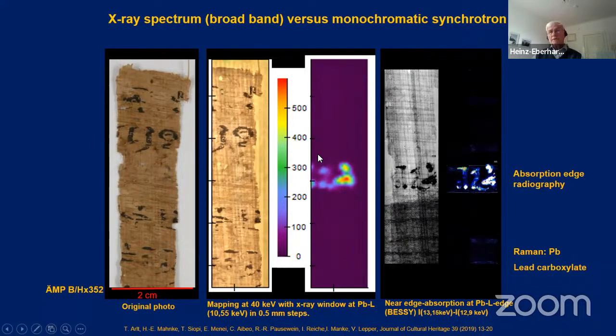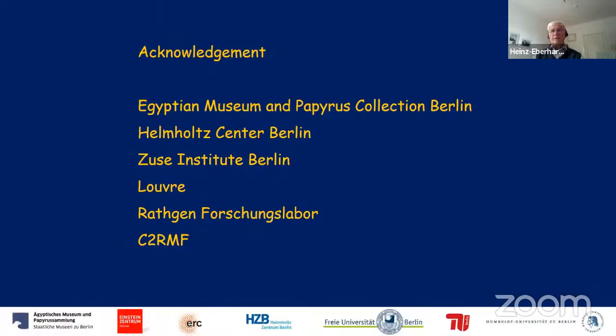One can see it much better, of course, much clearer, with better equipment on a synchrotron beamline, where you have the sharp focus and where, in fact, we did the L-edge sensitivity, going above the edge and going below the edge, subtracting it. Then we could see and identify the lead ink written symbol over here. And that ends my contribution.